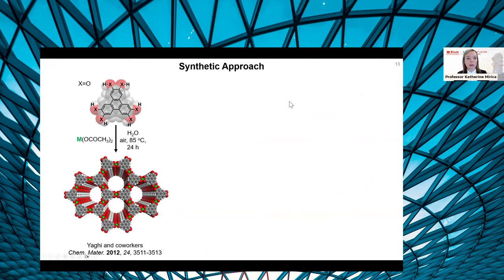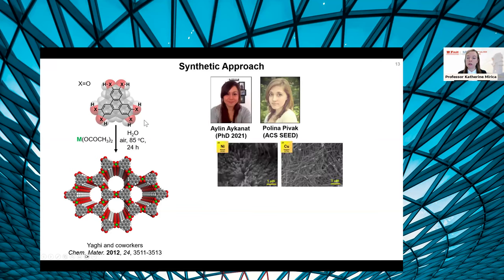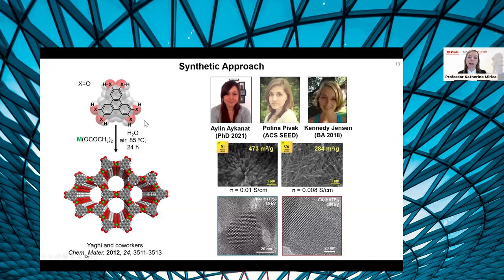A really useful feature of some of these conductive metal organic frameworks is that they're really straightforward to make, and the synthesis results in very robust water and air stable framework materials. So for example, starting with a hexahydroxy triphenylene ligand, which is commercially available, and reacting it with metal acetate salts in water under air, we can obtain this conductive porous framework material using basically the original or slightly modified conditions that were developed by Omar Yaghi during the first report of these framework materials in 2012. We can do this with graduate students, undergraduates, as well as high school students in my laboratory.